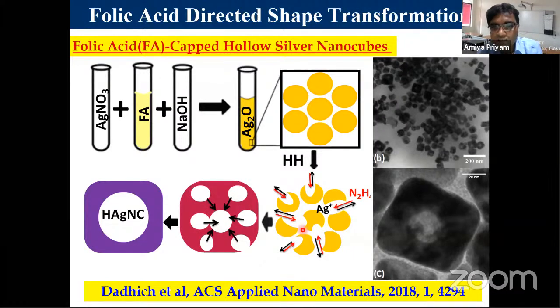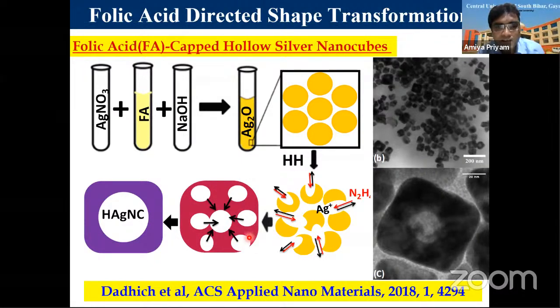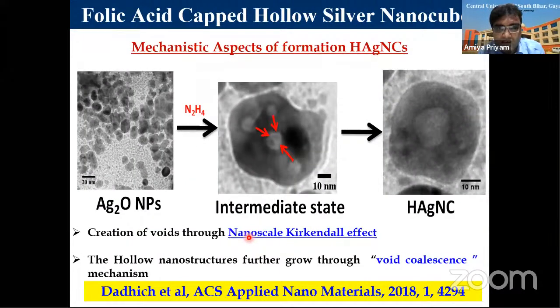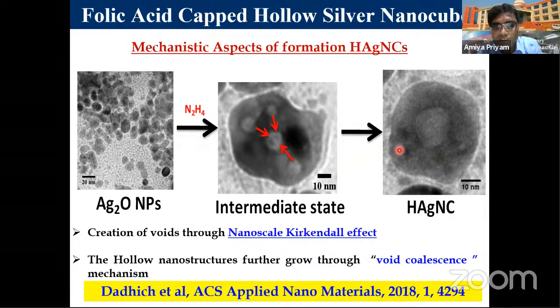And we could also prove it. These are the TEM images, and we also suggested a mechanism, which we call the void coalescence mechanism. All the details are in the paper, and we got proof of our suggested hypothesis in the form of TEM images. You can see that initially small voids are formed in a crystal, and these voids fuse together to give a larger void in the center. So this is the mechanism of the Kirkendall effect that is prevalent in the synthesis of hollow nanocubes of silver.